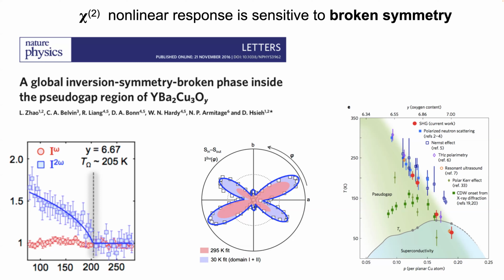And so I don't think we still understand this, but they saw something very similar in iridate compounds. They also saw a phase, in Hsieh's group, which showed that there was an onset of a second harmonic generation signal, which meant that there was some kind of structural transition, which nobody had found before. And then they went, with very, very sensitive X-ray diffractometers, and found and confirmed that it was there. So it was not the kind of thing that you could see casually, but you can see it in the SHG quite clearly. Okay, good.